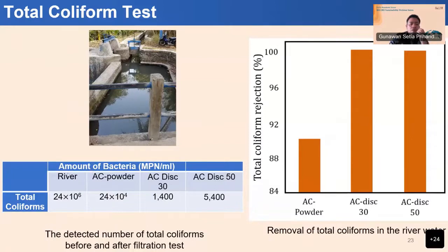And then we check the amount of bacteria inside the river, and it's about 24 million. After that we check the water permeated from the activated carbon powder, and it gently decreases. And then we have the best result when we use a AC-disc 30. So before it was 24 million, and now the bacteria inside the water after the filtration is only like 1,400. So it rejected 99.9% of the bacteria inside the water.